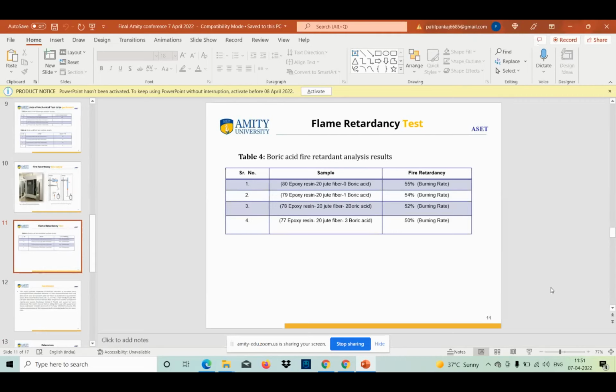In the burning test we will record the results of the fire retardancy testing. For the sample with 80% epoxy resin, 20% jute fiber, and 0% boric acid, the burning rate is 55%. After that we increase the boric acid. As the percentage of boric acid increases, the burning rate slightly decreases. At the last sample, the fourth concentration, with 77% epoxy resin, 20% jute fibers, and 3% boric acid, the burning rate is 50%. So as we increase the percentage of boric acid, the burning rate decreases.